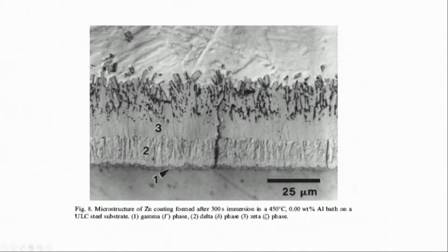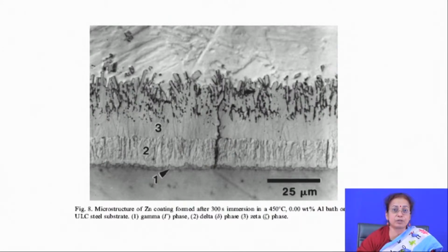Fine cracks are not good because they create a path for the transportation of water molecules from the environment, but it is still acceptable because zinc also saves the surface by the process of sacrificial action. So, even though there are possibilities of formation of a lot of intermetallics at the interface which are brittle in nature, and whose presence can cause crack formation at the interface, it is still acceptable as it is a zinc coating, because zinc offers sacrificial action to save the underlying substrate.